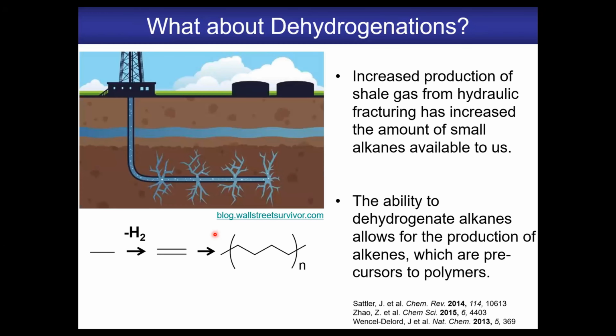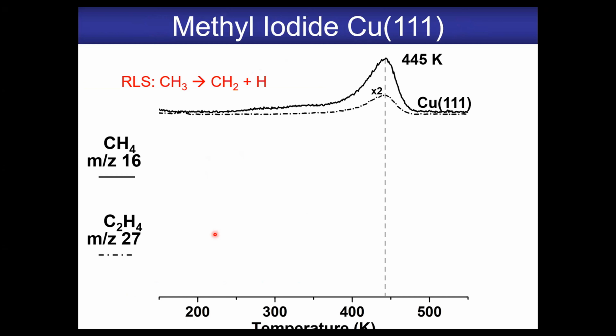So that was hydrogenations. What about dehydrogenations? There's a big interest with shale gas, CH activation, and also making alkenes to go into polymers. So CH activation is rate limiting typically, and coking is a big problem because you need to use reactive elements for this. So what I'm showing here is experiments we're doing with methyl groups that we add to the surface via dissociating methyl iodide. And on a copper surface, you have to heat it up to about 450 Kelvin to break CH bonds in the methyl groups to basically make hydrogen, CH2, and then make ethene and methane. So this is basically a reporter of the temperature which CH activation happens on copper.